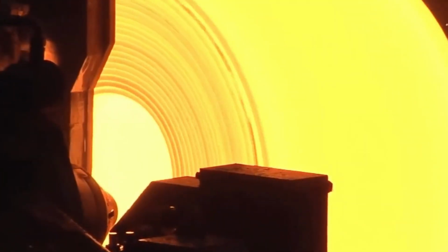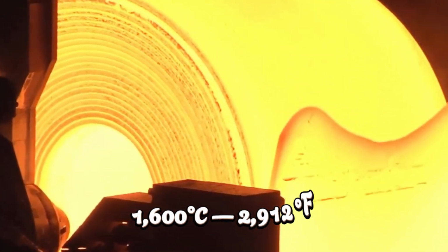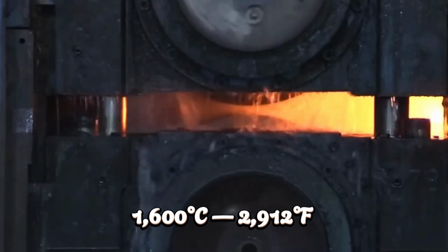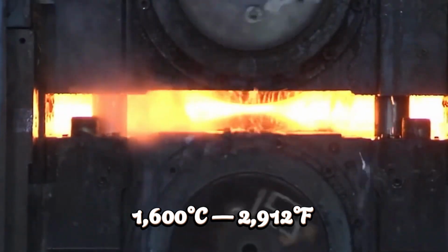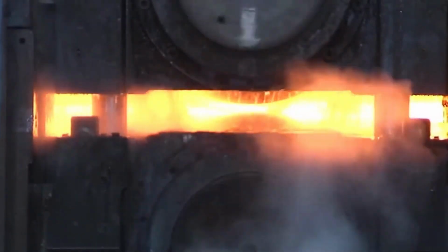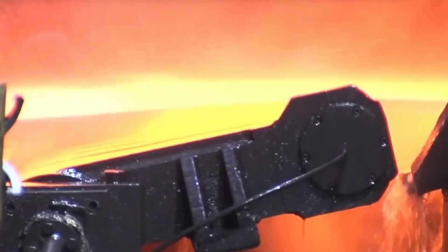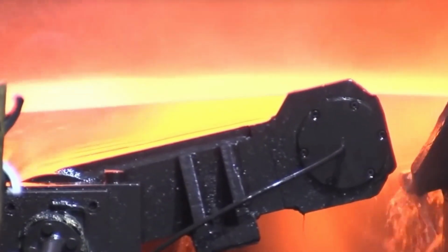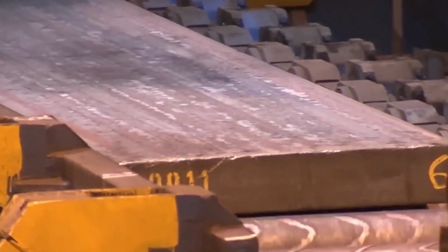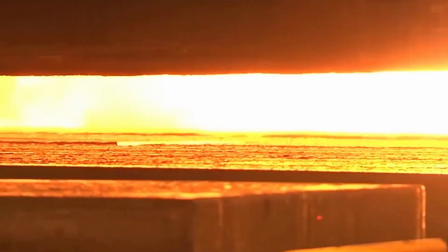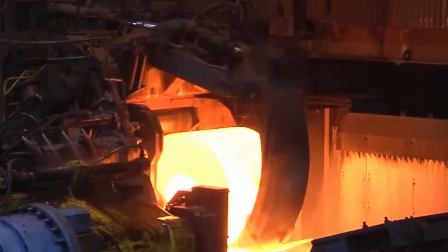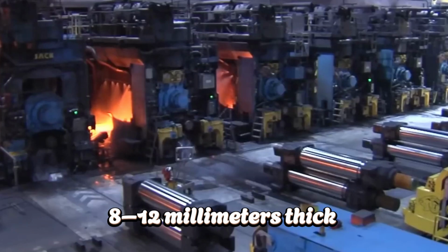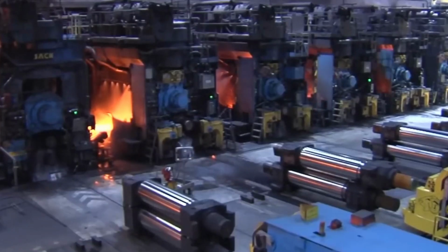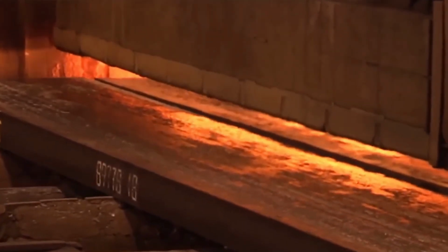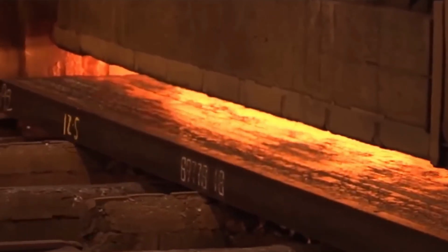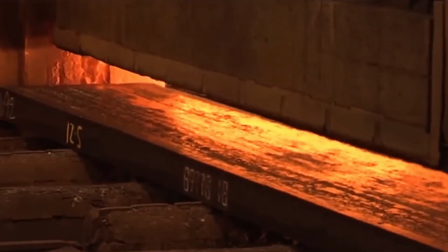Liquid steel enters this mold at 1,600 degrees Celsius, 2,912 degrees Fahrenheit, hotter than volcanic lava. This is the first step in how modern steel beams are made inside a continuous casting line. The shell forms just 8 to 12 millimeters thick, and if it sticks for even a moment, the entire strand tears. Here's how the beam survives the line.